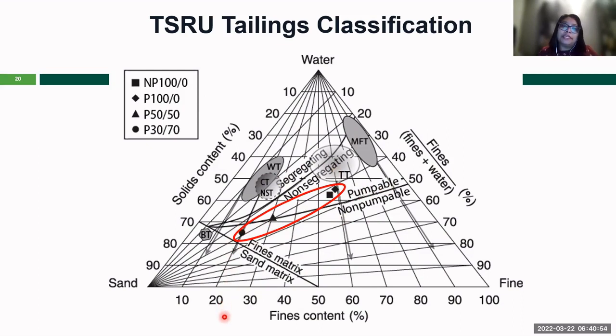pumpable data points. And if you now look at our 100% polymer data, the sample is slightly desaturated, thick and tailing material. TT is defined as thick and tailing, so this data point is close to that TT. These arrows are the direction of desaturation for these materials. And the 50% sample is between the CT and NST, which is composite tailings and also non-segregating tailings.